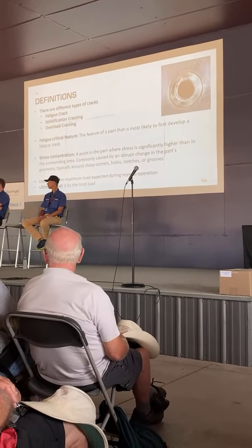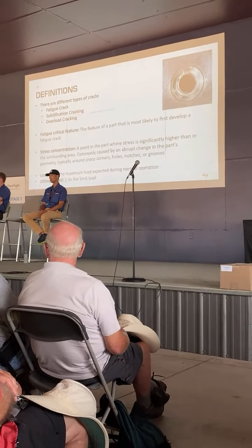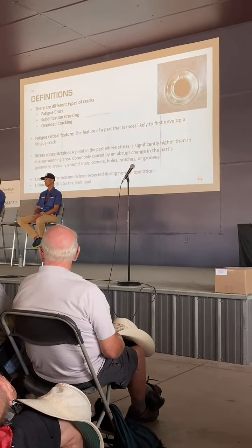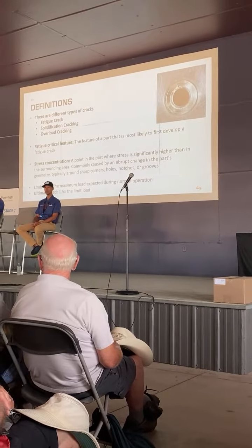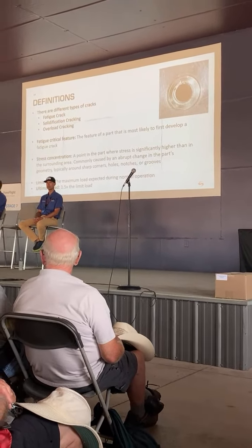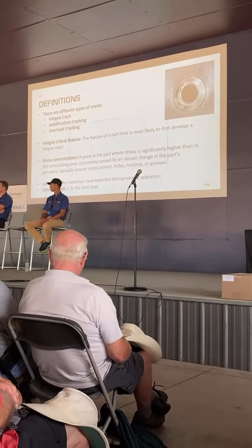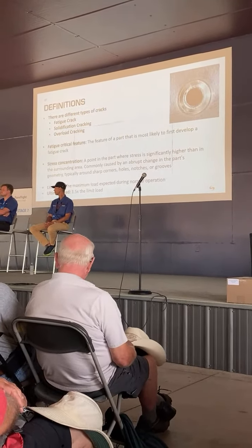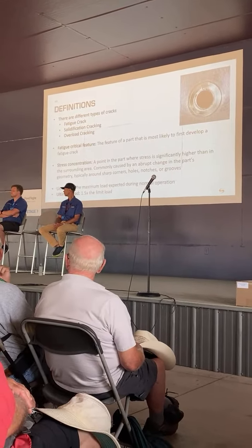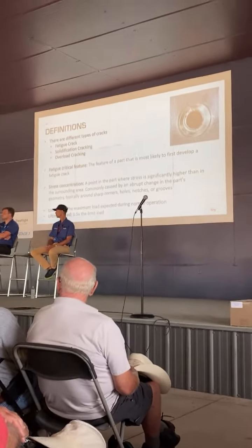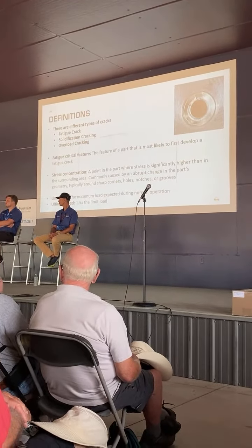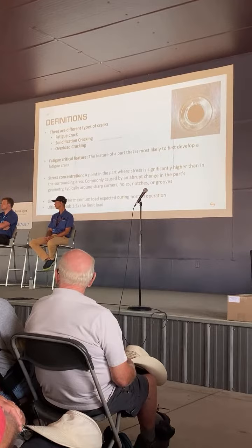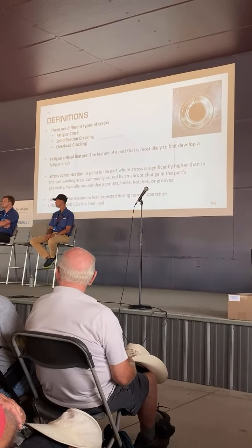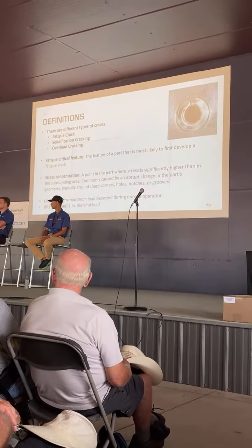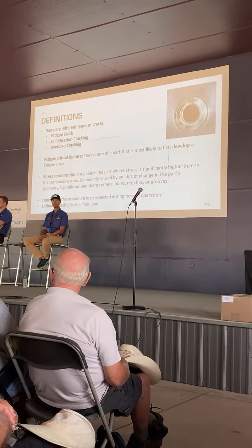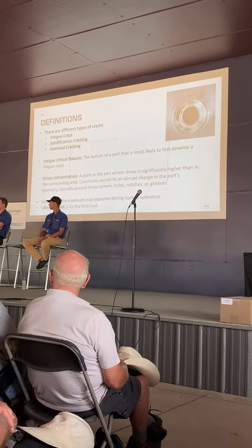The fatigue critical feature, a part may have many features. For example, the notch, relief notch where flanges are bent. It may have other features in it that raise the stress level around that particular feature. So the fatigue critical feature, many things could be features that eventually cause fatigue. That are normally in parts as well. Aluminum will eventually fatigue as you go long enough. The point is to design it in such a way that that doesn't happen within the useful life of the airplane. Stress concentration. So a point in the part where the stress is significantly higher than the surrounding area.